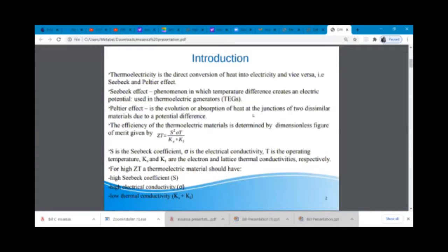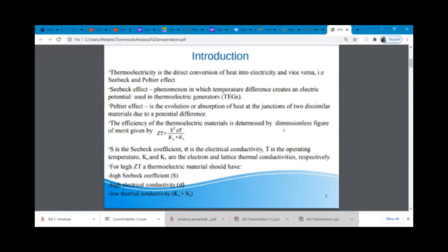So the efficiency of thermoelectric materials to do the conversion is determined by the so-called figure of merit, ZT, which is equal to the Seebeck coefficient squared times the electrical conductivity times the temperature, all over the total thermal conductivity, Ke plus Kl, where Ke is the thermal conductivity due to electrons and Kl is the thermal conductivity due to lattice vibration.